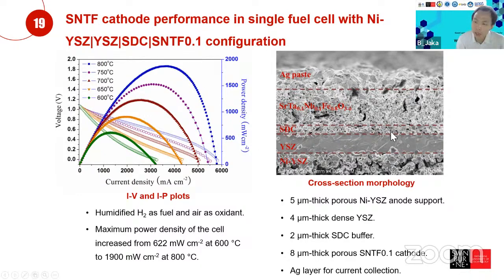And these are the SEM images of the structure of the full cell in here. So we can see that the anode side has a well-tailored structure, meaning that it has a progressively different structure. So this Ag paste is used as a current collector, and then this SNTF is used as the porous cathode layer, and then we have another layer which is the SDC in here, which is coupled with the YSZ in here. Okay, and then NiYSZ in here.